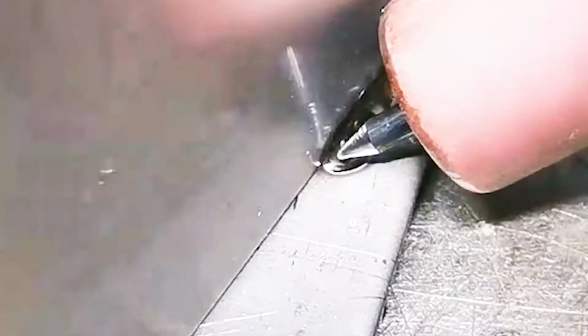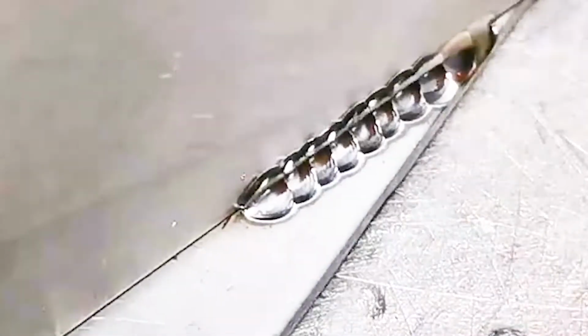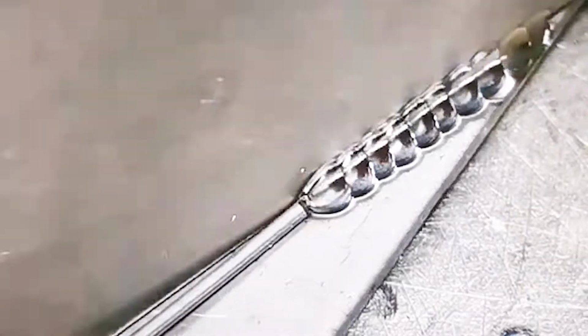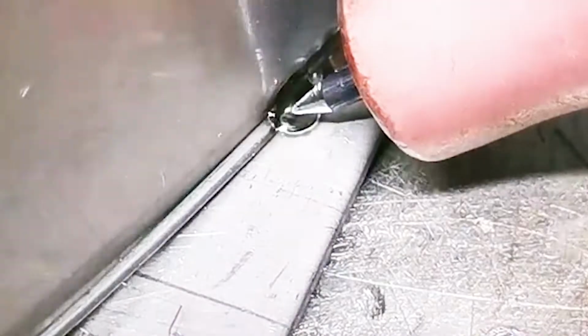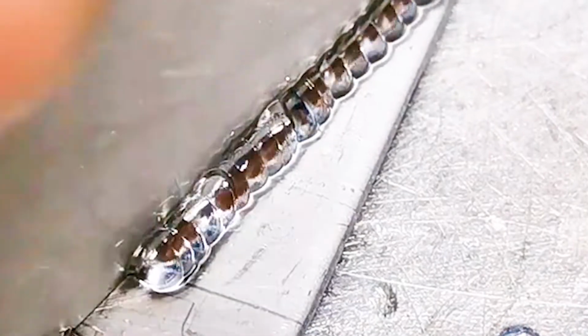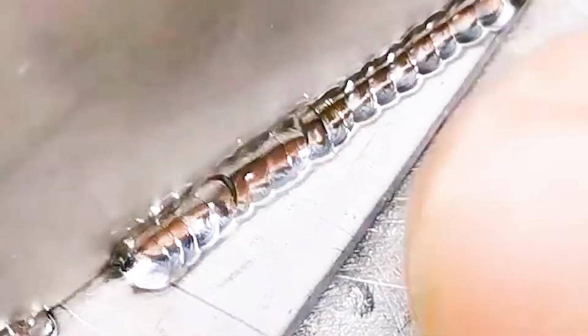2. Possible phenomena: black or yellow solder joints. 1. Reason: the exposed part of the tungsten needle is too long, resulting in insufficient argon protection. Solution: readjust the tungsten needle to keep the exposed part at about 8 mm. 2. Reason: the output power of the cold welder is set too large. Solution: adjust the pulse time and pulse current of the machine.